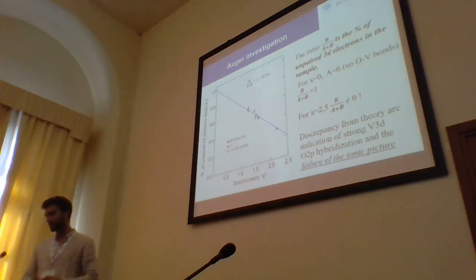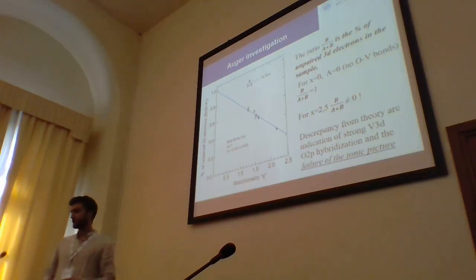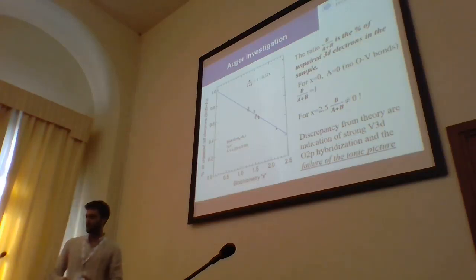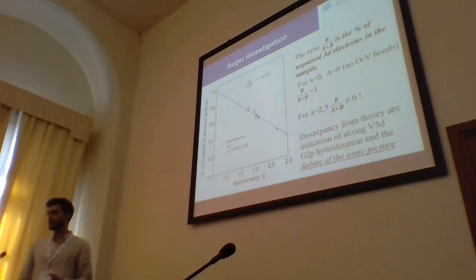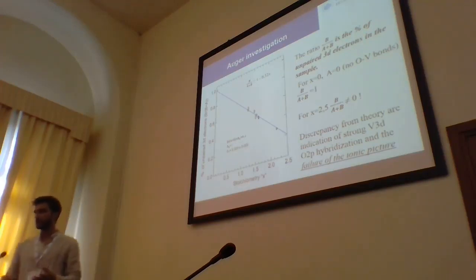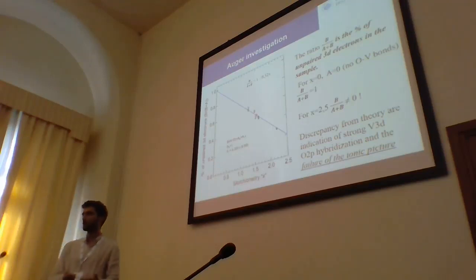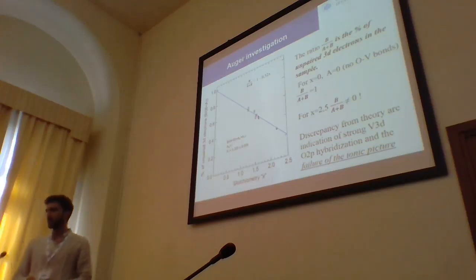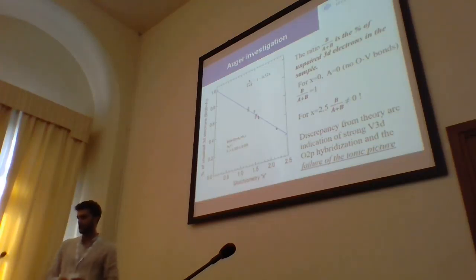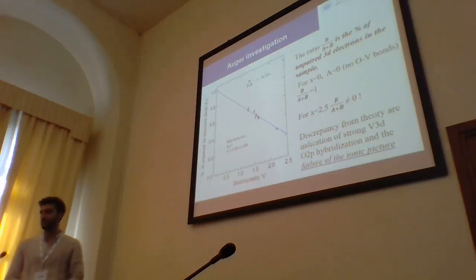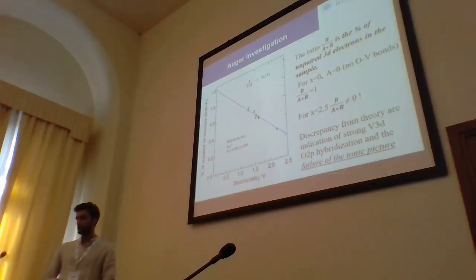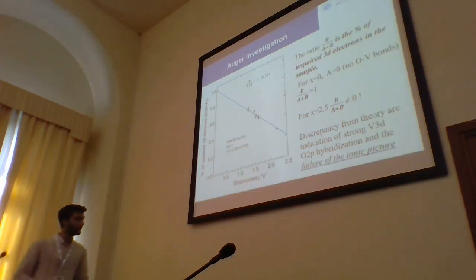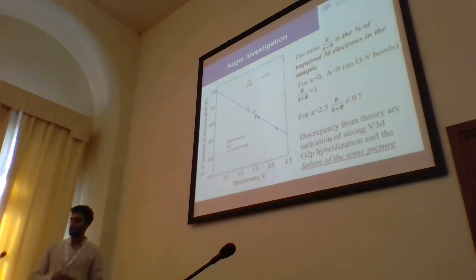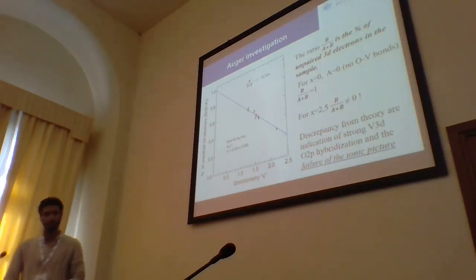The particularity is that for stoichiometry 0, which means without oxygen, the fit goes to 1, since all the electrons are unpaired. There is no oxygen available to bond. So the A contribution is 0, and then we have B over B, which is 1. But for the maximum oxidation state, we shouldn't have unpaired electrons, but we actually have a value which is 0.2, which is a fingerprint of a strong vanadium 3d oxygen 2p hybridization, and it points out a failure of the ionic picture to describe the vanadium oxide valence band features.